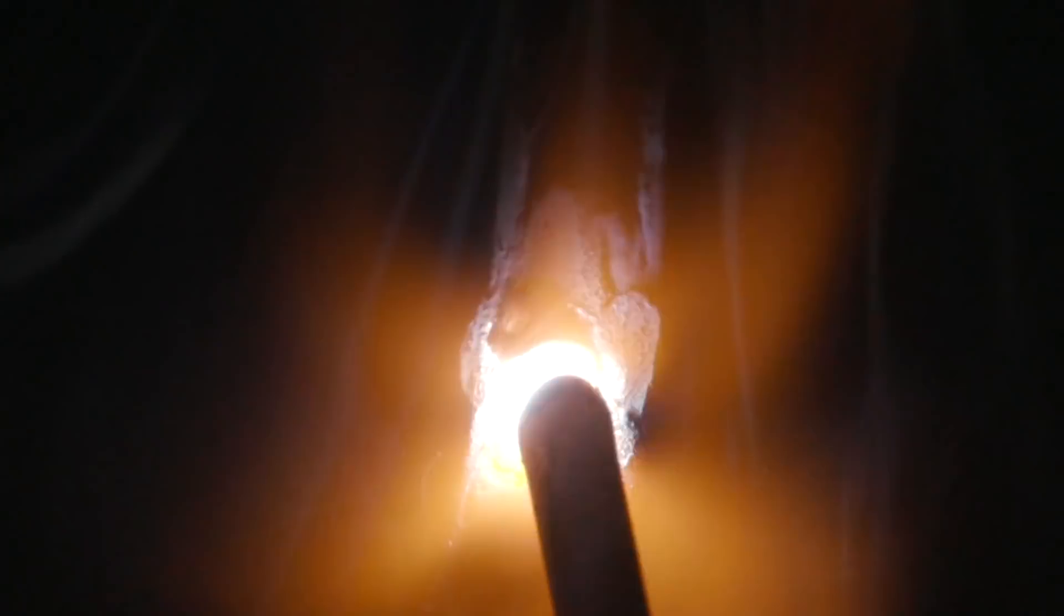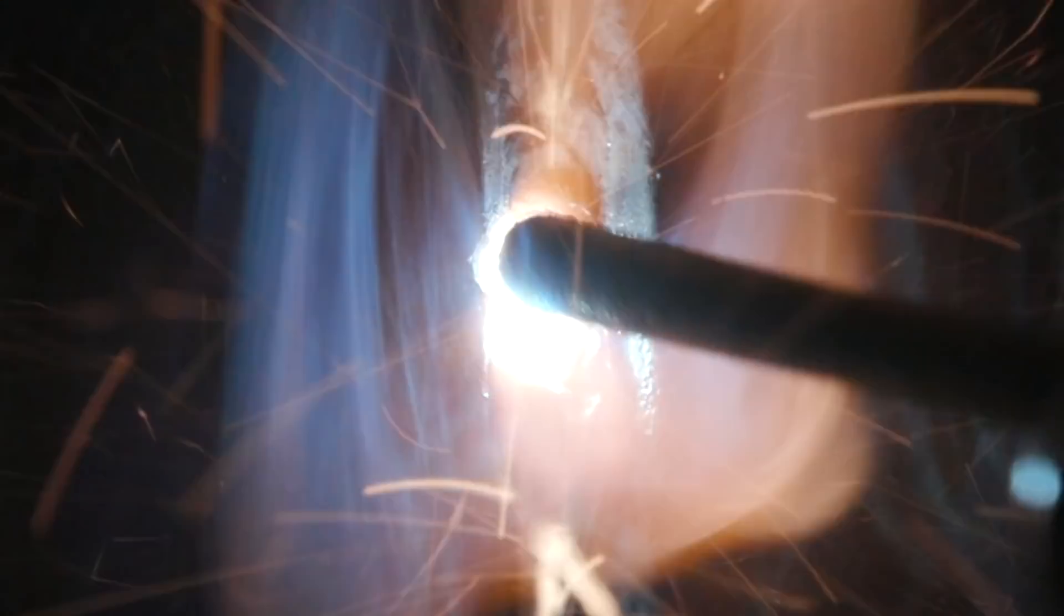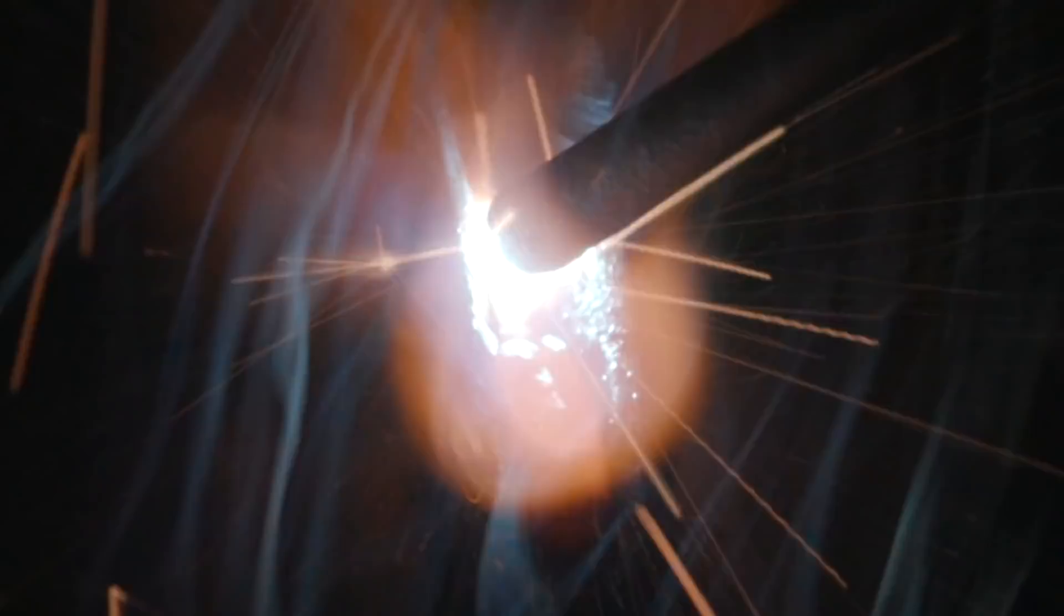I'm ready for a hot pass here because if I tried to just cap this off, for me, I don't feel comfortable carrying that much metal in that deep of a groove. I realize this is schedule 80 and I do have some mass there, but I just want to put a quick fill hot pass in here. I don't mind running these half burnts. I'm real confident that I'm going to get to the top with a little half burnt rod and that's cool.